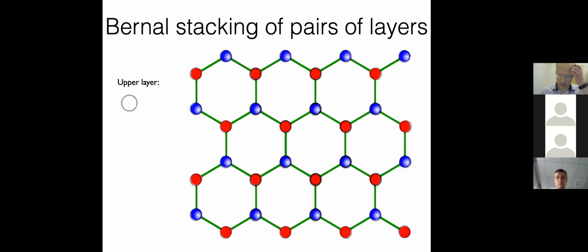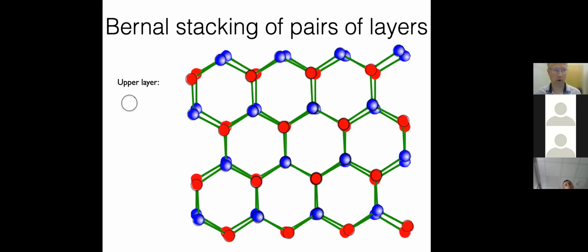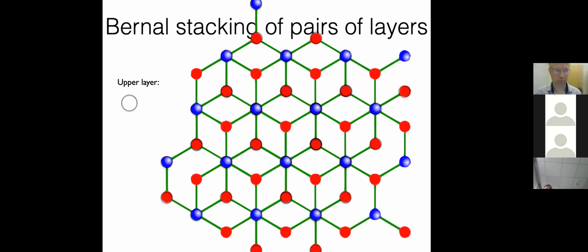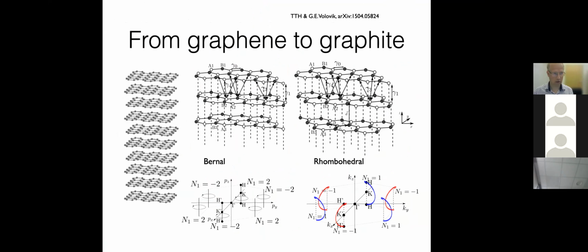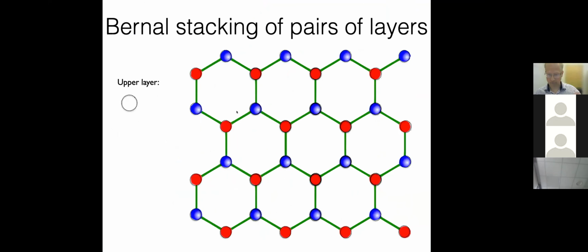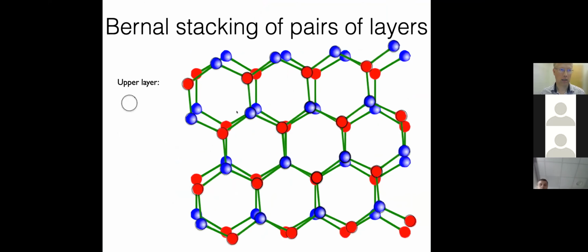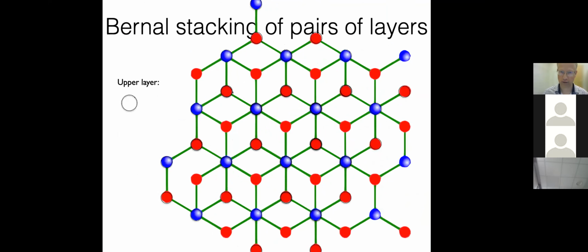Let's start from stacked graphene. What happens if you put two graphene layers on top of each other? The energetically favorable configuration is not the one where the honeycomb lattices are exactly on top of each other, but rather where they are shifted or rotated with respect to each other, so that one pair of atoms, let's say the blue and the underlying red atom, are on top of each other, and then one atom is on top of the hexagon on both lattices. And this is how you construct every pair of graphene layers.